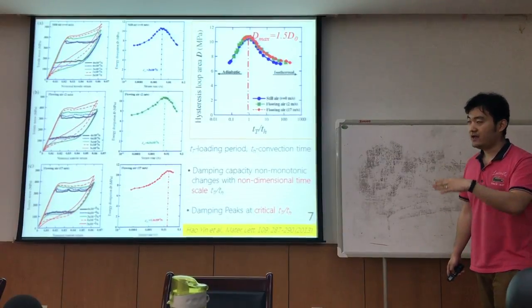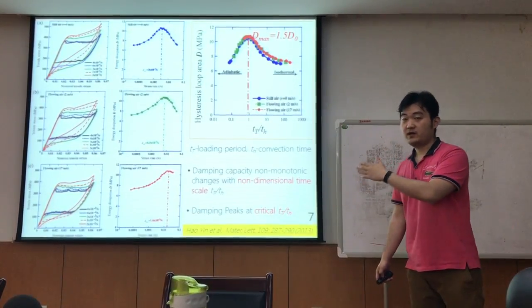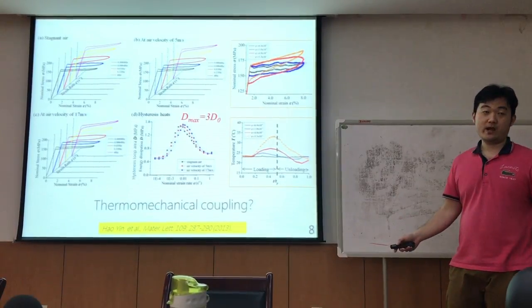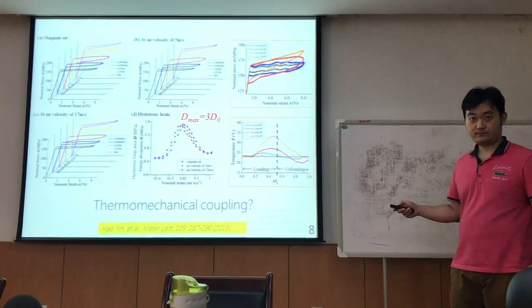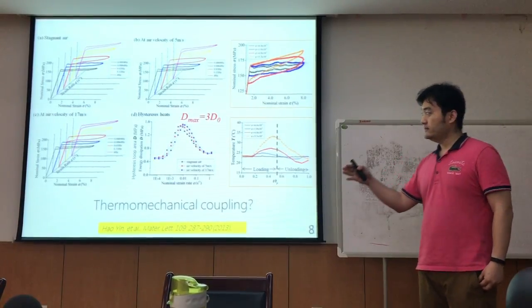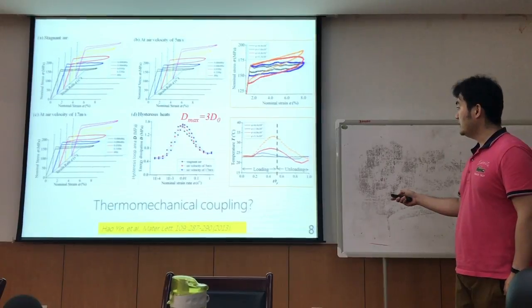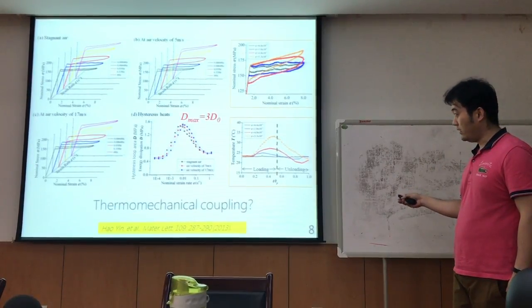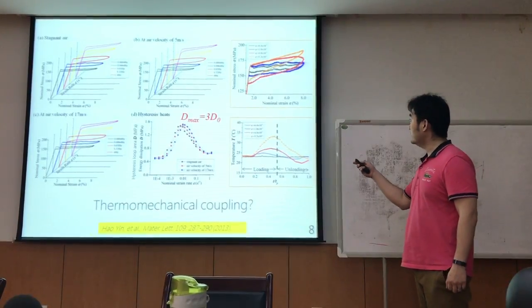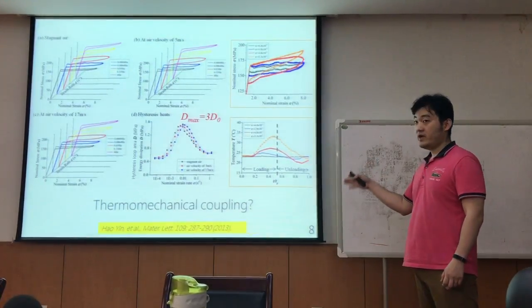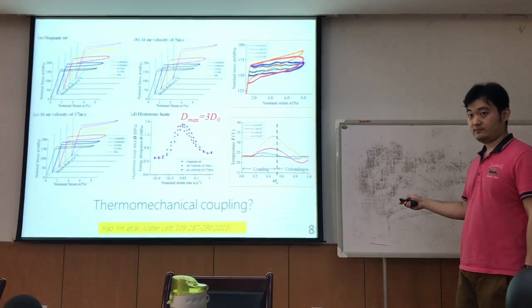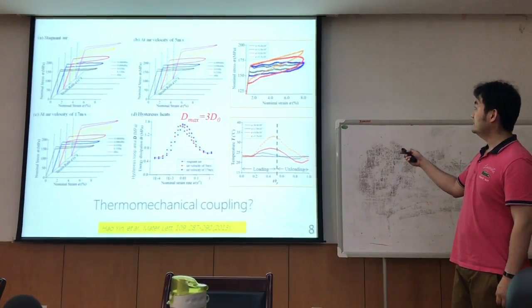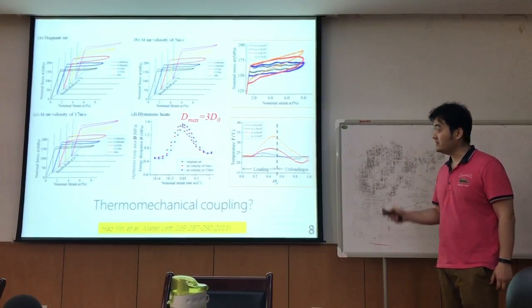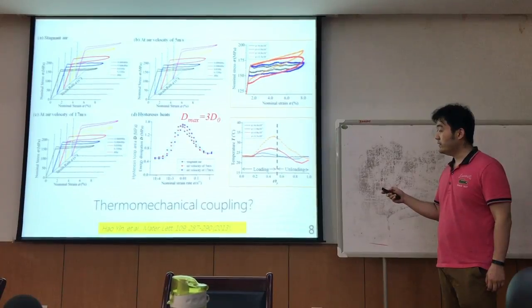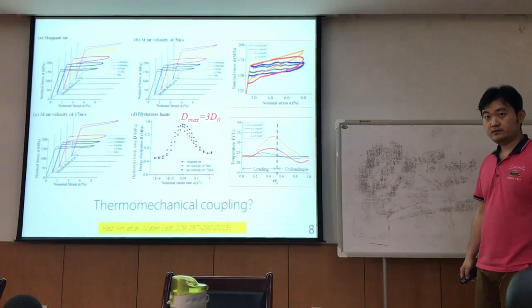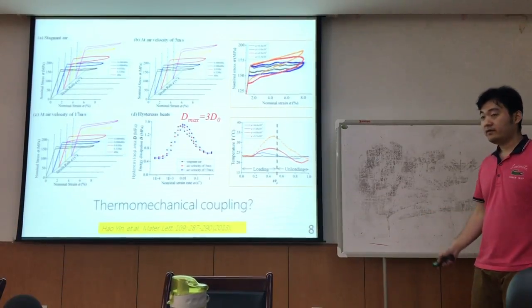How about the copper, aluminum, nickel single crystal shape memory alloy? They have similar results. But this time we record the surface temperature. We find out the temperature varies. Then we know the reason for these stress strain curve variations is the temperature. So the temperature affects the stress strain curves. But this is one-way effect. This is not thermomechanical coupling.